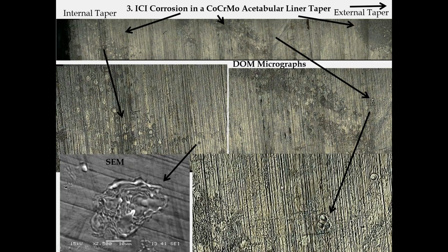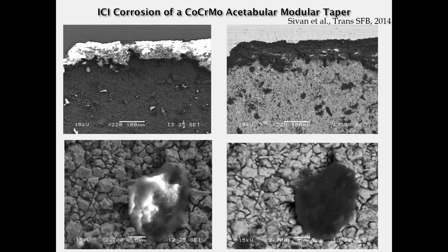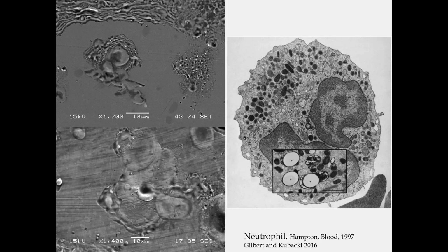So these phagocytic cells can migrate into modular tapers, and we've seen multiple cases of these cell-like biological remnants inside these modular taper junctions, driving corrosion of that cobalt, chromium, and titanium surface. And so just to show an example, we have the neutrophil in TEM here, and corrosion patterns on cobalt, chromium, and I believe this is titanium.